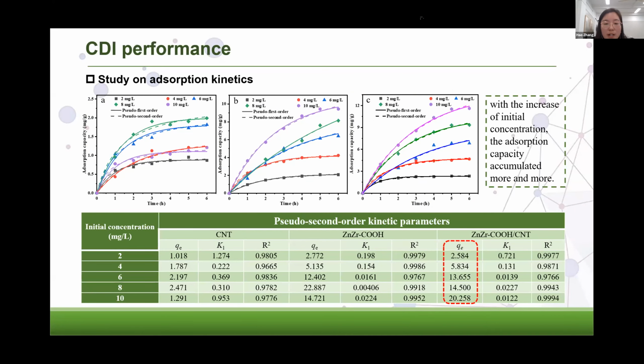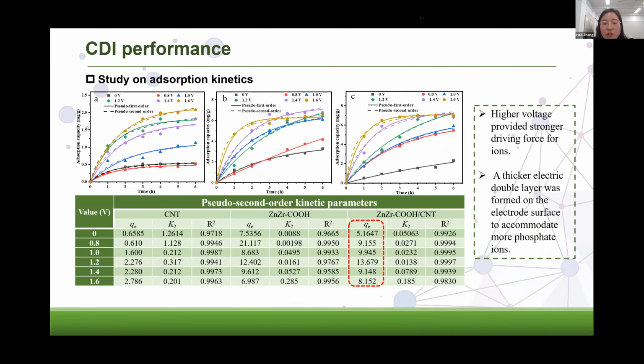By calculating and fitting the above measured data, we obtained the adsorption kinetic curves under different initial concentrations and voltages. The results show that the adsorption of phosphate on the three electrodes followed the pseudo-second order kinetic model. It indicated that with the increase of initial concentration, the adsorption capacity accumulated more and more. In these figures, it was observed that the higher the voltage, the faster the adsorption rate, and the faster the adsorption equilibrium was reached. Higher voltage provides a stronger driving force for ions, and a thicker electric double layer was formed on the electrode surface to accommodate more phosphate ions.